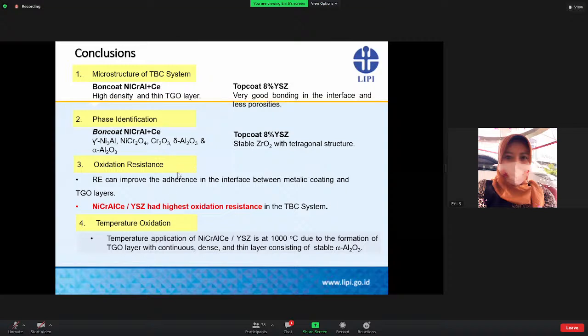From the oxidation resistance, we can understand that the reactive element can improve the adherence at the interface between the metallic and the ceramic, and also the TGO layer. And the sample with the addition of cerium as the reactive element had the highest oxidation resistance in the TBC system. For the oxidation temperatures, as you already know from the previous slide, 3 variations of temperature were selected, and the result shows that 1000 degrees C is a better and more appropriate temperature, due to the formation of a continuous, dense and thin TGO layer consisting of stable alpha alumina.